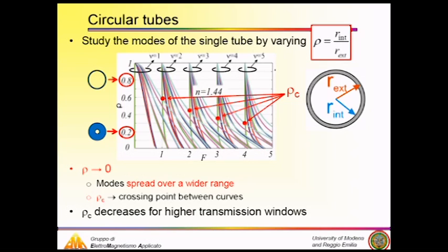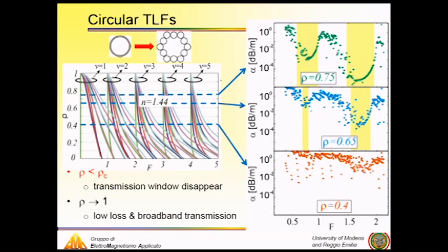So let's take a look at what happens when we apply this model to our microstructure fiber. Here you can see a comparison between three similar kinds of structures with different rho values, in particular 0.75, 0.65, and finally 0.4. And as predicted by our model, as the rho value is reduced, the transmission window tends to first decrease and then finally disappear, which justifies our model. So in conclusion, in order to have low loss propagation and broadband transmission, it is important to work with rho values which are as close as possible to 1, which means very thin structures.